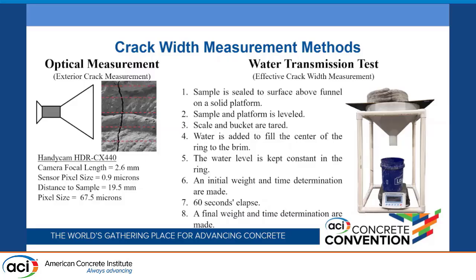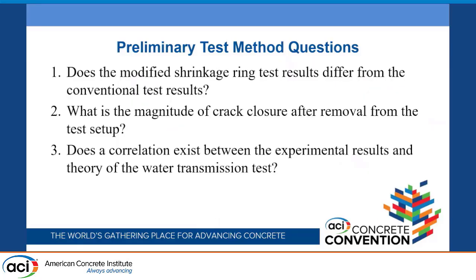In this test, we placed our shrinkage ring sample on an impermeable surface, centered it, and filled it with water. We keep it at a constant water head and allow that water to transmit through our crack. It goes down into the funnel and collects in a bucket on a scale, and we measure the weight change through time to calculate our flow rate. Pretty simple, relatively easy, but it gives us some pretty reliable results.